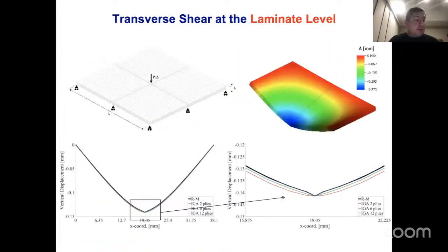Now, one of the natural questions that the composites community always asks is when you start getting to laminates that are thick. Each individual ply is very thin, so there is no reason to say that there's a significant amount of transverse shear, but when you put all the plies together, you get a thick laminate, and of course, transverse shear plays an important role. And so, to understand what's going on, we basically build up a plate like this, where we keep the thickness constant, and then we use more and more layers to represent that plate.